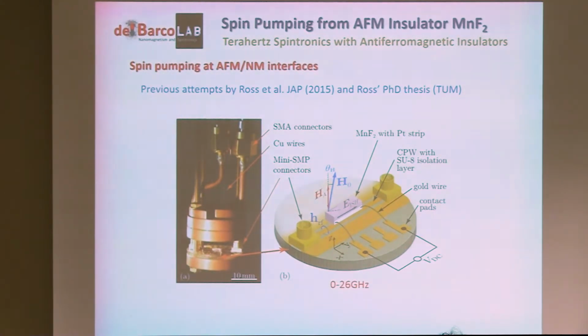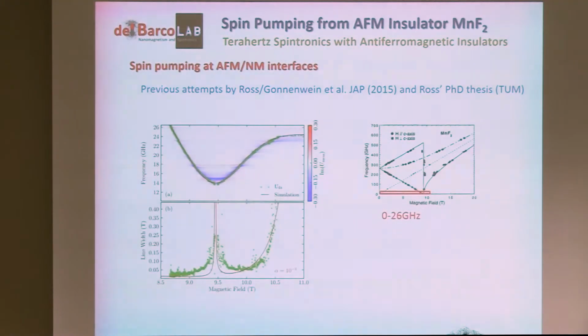They were limited to 26 gigahertz. This is the problem of working with coplanar waveguides, but in principle, this is doable. It's well designed. It's actually a very nice experiment. They did ferromagnetic resonance. They were limited to this energy, so they're only able to resolve what happens around here. But still, they do this very well. They see this resonance very nicely. They can actually look at the width of the resonance in different cases. I remind you that this corresponds to the spin-flop transition.